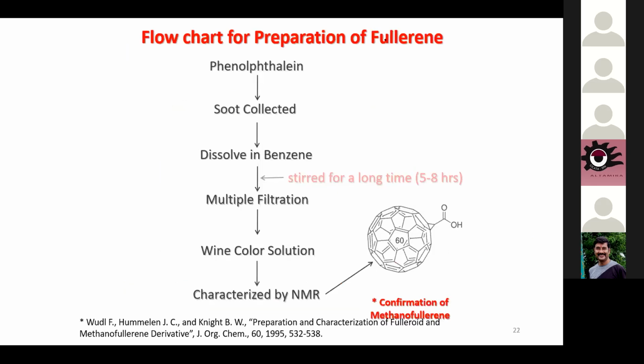This we have prepared in our laboratory itself. We have taken phenolphthalein balls and we collected a soot by burning, and we dissolved the entire soot which we have collected into the benzene, and we stirred around 5 to 8 hours. After preparation, we got the fine solution. In NMR, we got that the structure which we obtained was methanofullerene, close to fullerene, one of the isotopes of fullerene.